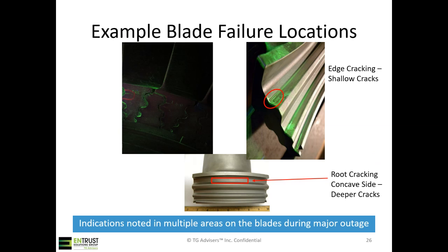The first two are NDE images showing locations of cracking. So there are cracks adjacent to the end faces of the blade root that were fairly shallow. That top right image shows it pretty clearly. And then there are also cracks on the concave side of the blade root there on the top lug area. You can't really see the crack in this image, but it's called out. The location's called out with that red box. But overall indications were found in multiple areas on these blades during an inspection performed during a major outage, and they were present on multiple blades throughout this stage.